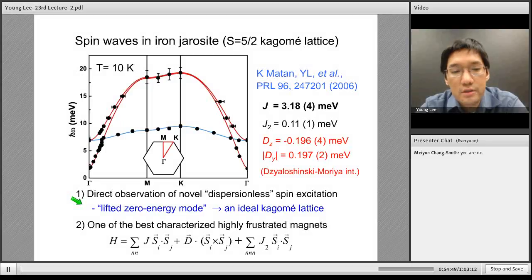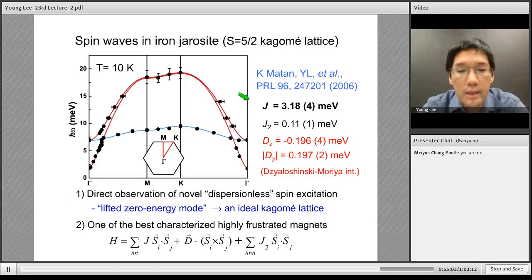And this is this lifted zero energy mode due to this ideal Kagome highly frustrated geometry. And the lines in this plot that I'm showing you are fits to theory, and we can now extract numerical values for the exchange parameters and the leading perturbation, the Dzyaloshinskii-Moriya interaction parameters. So it's also one of the best characterized highly frustrated magnets. And again, having neutron scattering of the spin waves on a single crystal is the best, bar none, method for characterizing such systems.